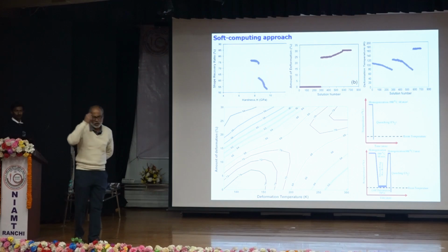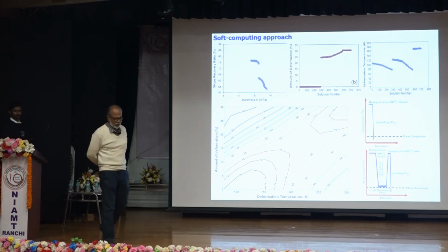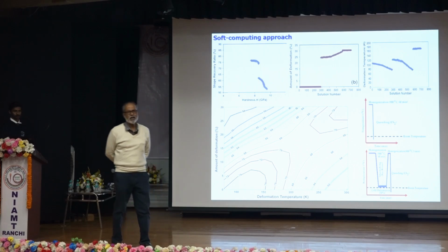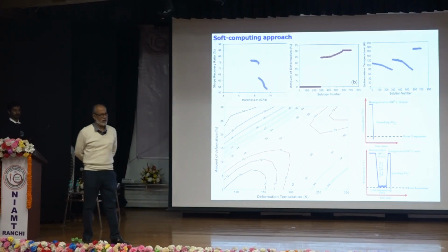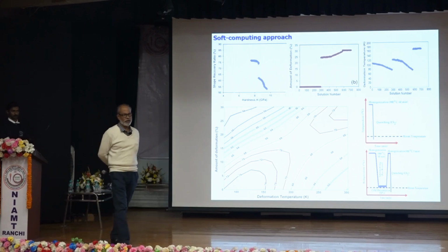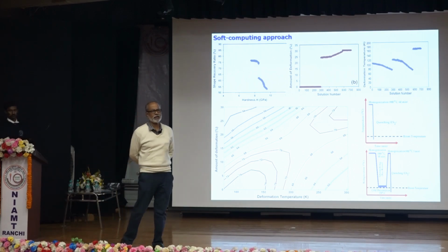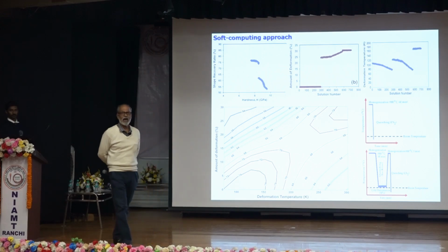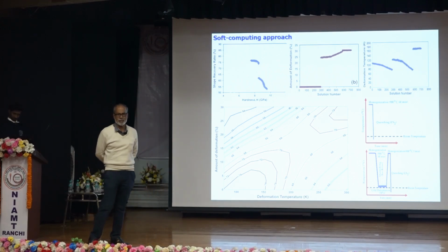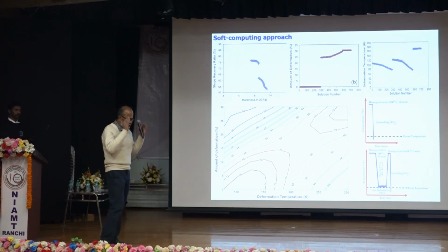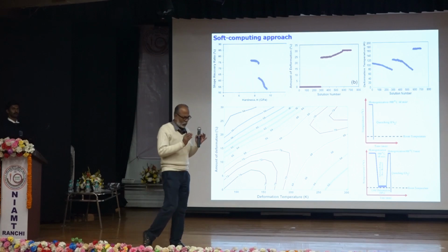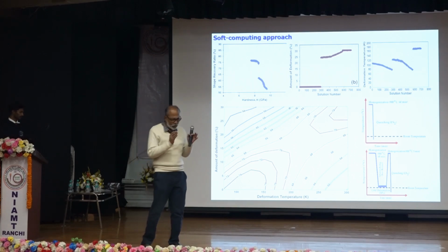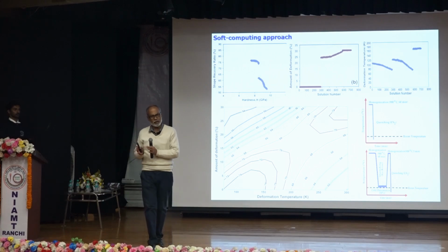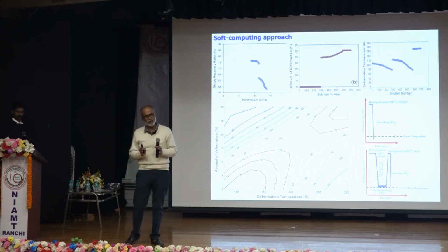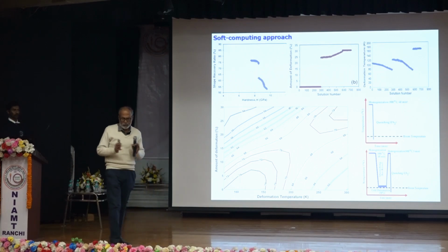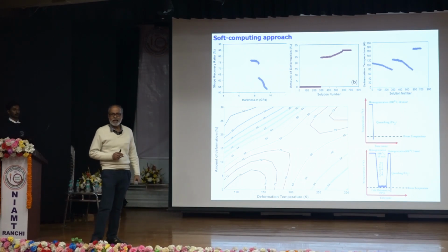As we were confused, the other supervisor, Professor Shubhabrata Datta, an expert in soft computing, collected the data and tried to correlate the input and output. Inputs were deformation amount, deformation temperature, aging time, and aging temperature. Outputs were hardness, elastic modulus, and shape recovery. They developed an ANN model with this input and output, and that model was used in an optimization experiment under a genetic algorithm framework using NSGA-II software to optimize the hardness and shape recovery.